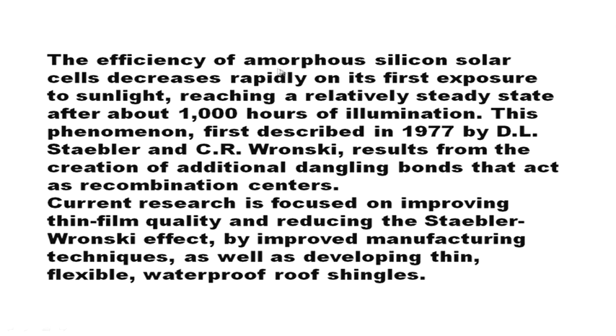The efficiency of amorphous silicon solar cell decreases rapidly on its first exposure to sunlight, reaching a relatively steady state after about 1000 hours of illumination. This phenomenon, first described in 1977 by Staebler and Wronski, results from the creation of additional dangling bonds that act as recombination centers. So, what happens? This is a very important phenomenon in the case of the amorphous silicon solar cell.